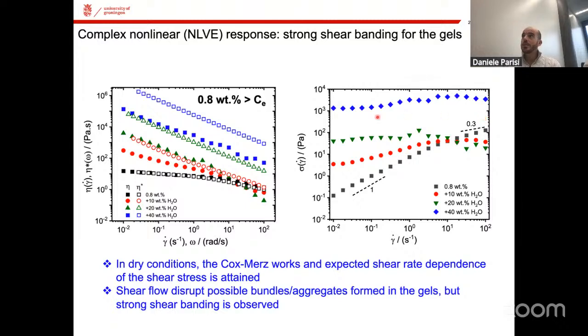However, when you have gels, you know that the viscosity is indeed decreasing, but the stress that the material exerts is just constant. And this has to do with the fact that there are a lot of instabilities of flow in these complicated systems. So this, for instance, in terms of printing design is also very important, because stress means the pressure that you need to apply to the 3D printer to let the gel come out from the die, right? So how strong you need to push if you want the system to get out?